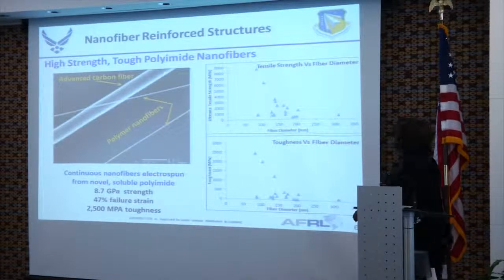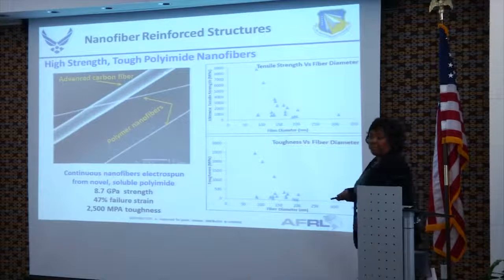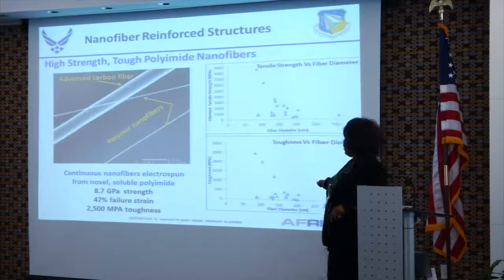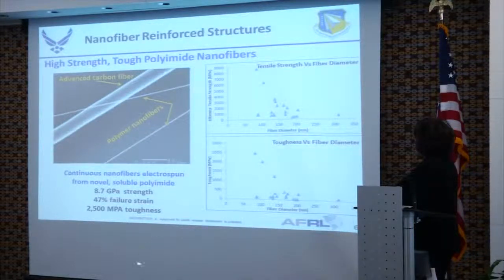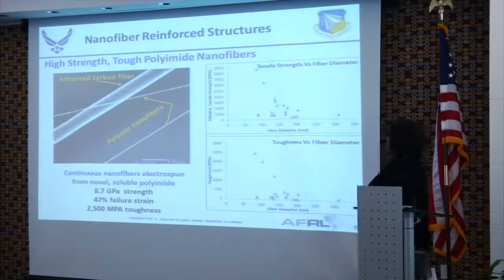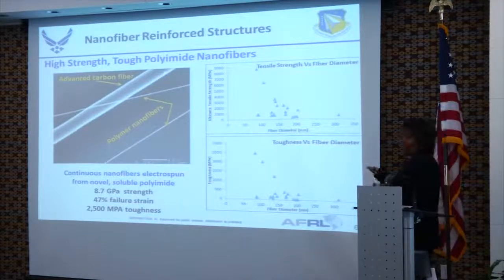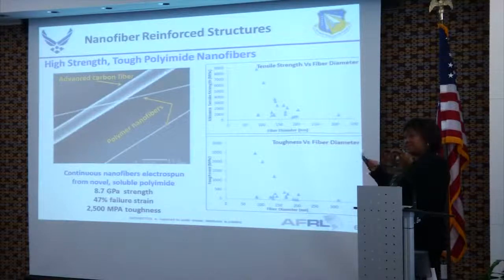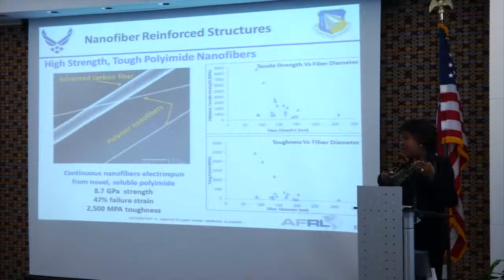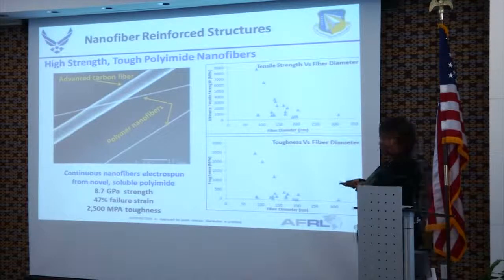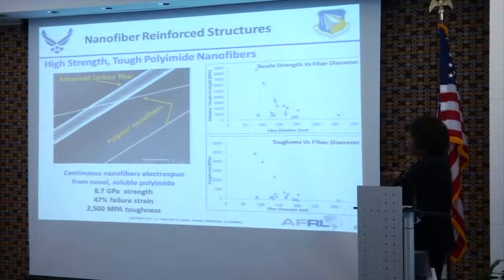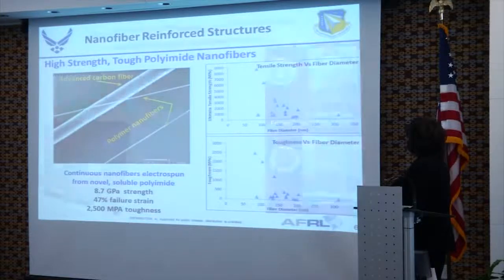What's also very interesting is that with this increase in strength, you usually see a fall off in the failure strain. But in this case, the failure strain actually increases. It's about 20% greater than you would expect to see, a strain of about 47%. So these are really new compositions of matter, with new processing to enable nanofiber fabrication. We've always wanted to get to smaller diameter fibers because the probability of defects in fibers goes down as you go to smaller diameter, and this processing enables that. And so we're excited to see where this goes as they continue to work on synthesizing and improving this processing and incorporating these into laminate structures.